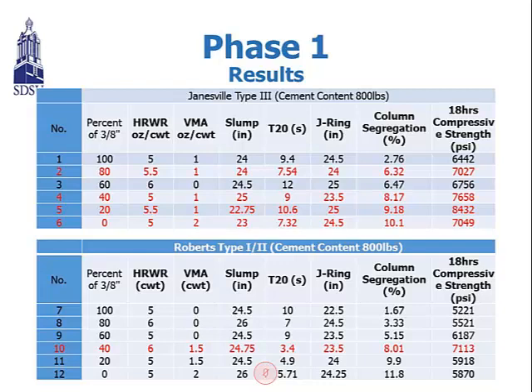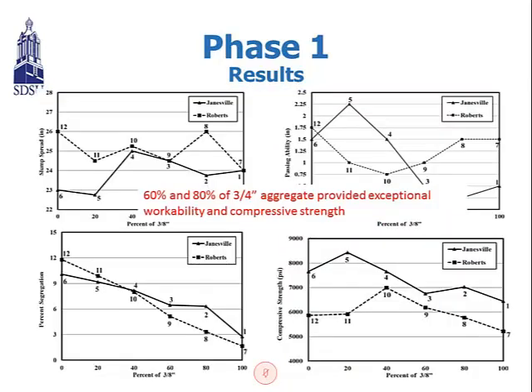As you can see in the table, we have the 12 mixtures, and we found the slump flow, T20, J-ring, column segregation, and 18-hour compressive strengths. And we realized that numbers 2, 4, 5, 6, and 10 have satisfactory strengths, which is greater than 6800 psi. We also show the results in the graph, and the results indicate that mixtures having 60% to 80% of the 3/4 inch aggregate provide exceptional workability and compressive strength.